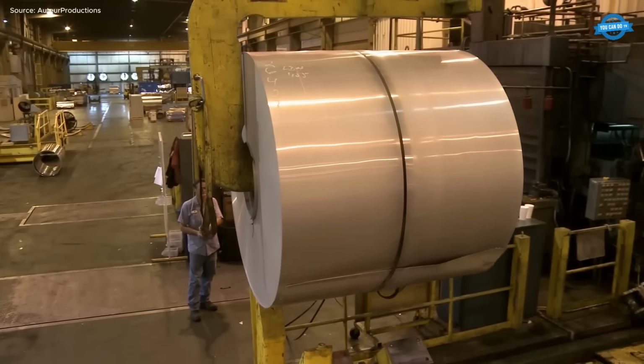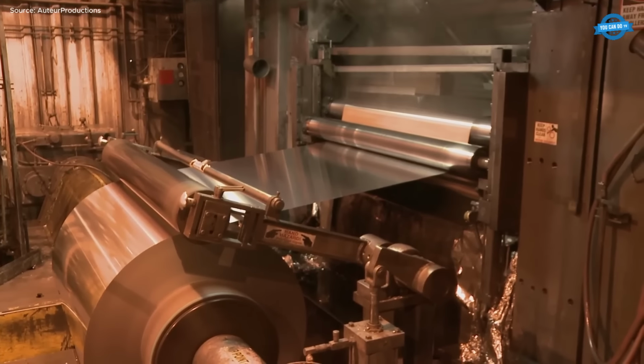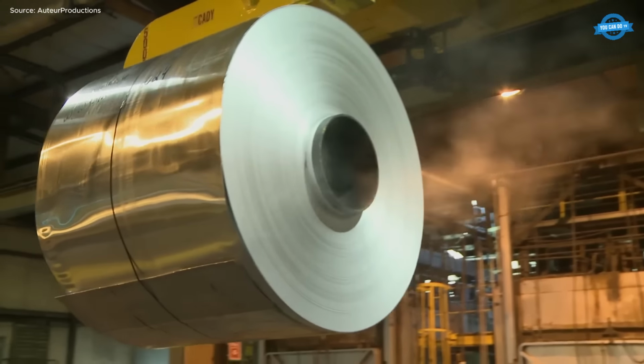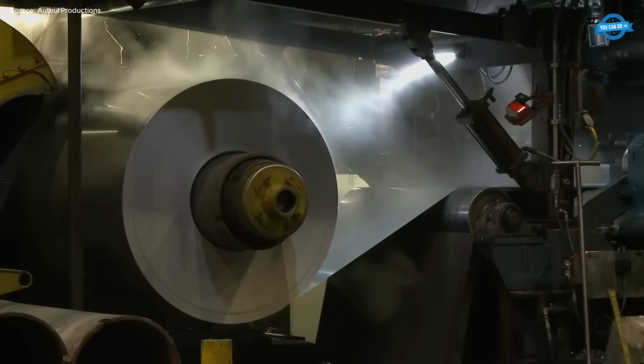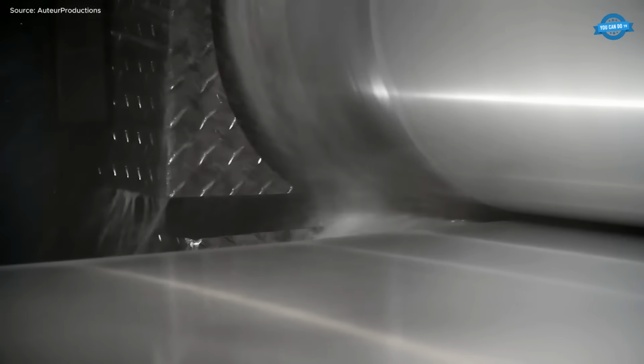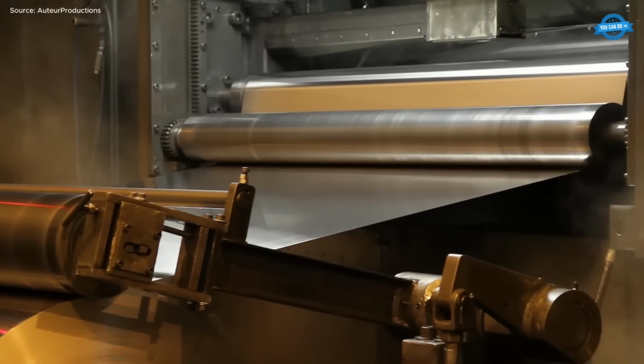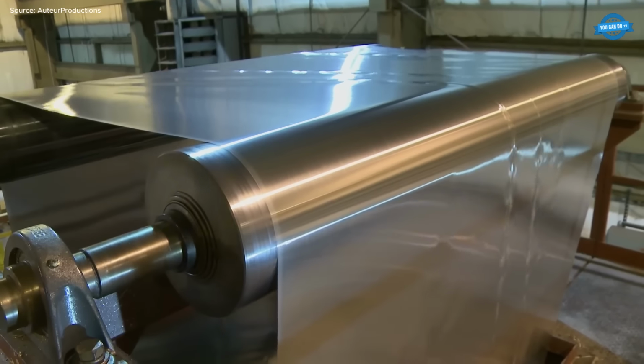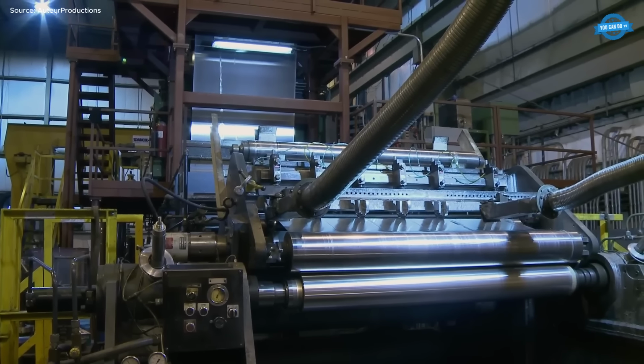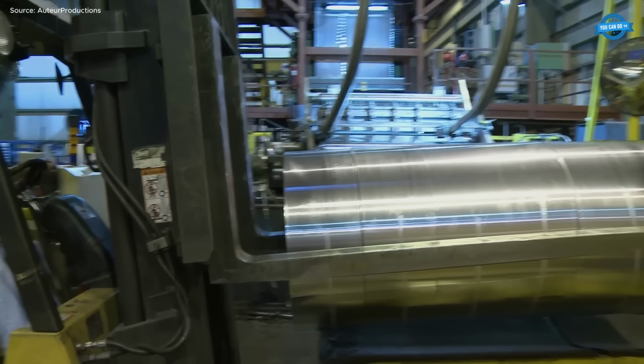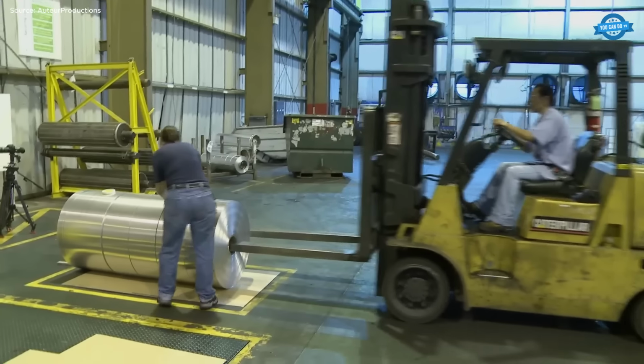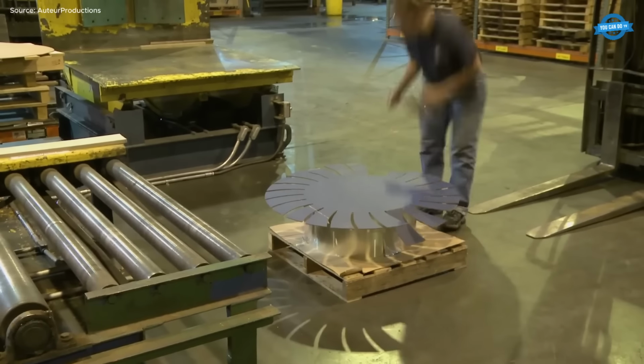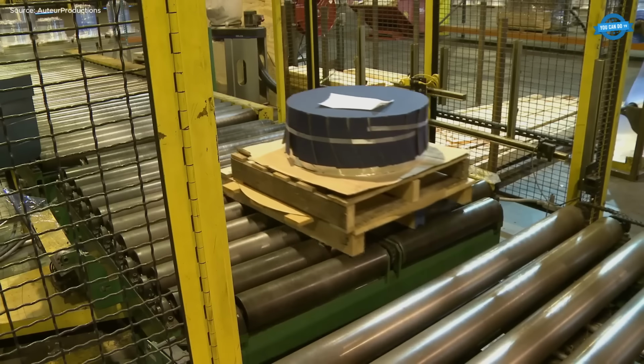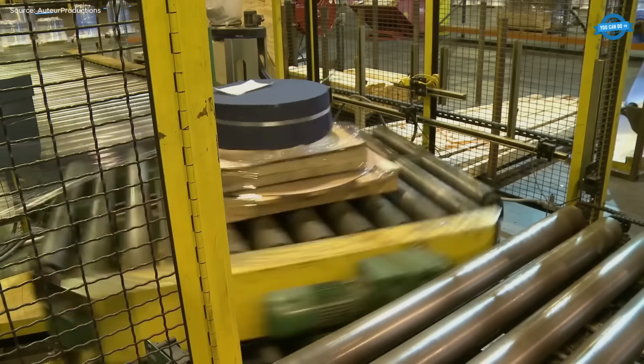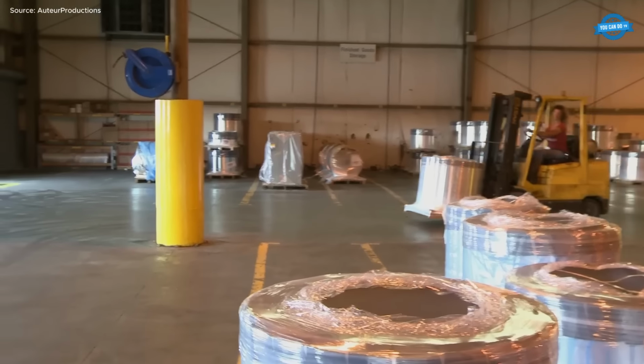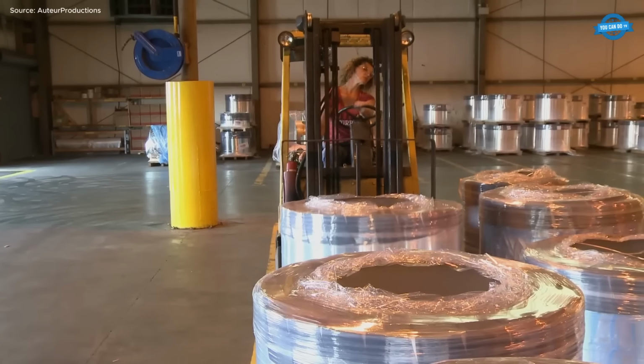Coils proceed to the cold mill for thickness reduction. After an initial pass, they go into annealing ovens to soften the material, enabling further rolling. The process continues through the foil mill, where aluminum is rolled to final gauge at speeds up to 2,000 feet per minute. Coolants control heat and maintain quality. Final steps include slitting, lubrication and testing: tensile, Olsen, elongation. Coils are weighed, shrink-wrapped, labeled and stored with full traceability before shipping, ready to become everyday products like cooking pans or packaging foil.